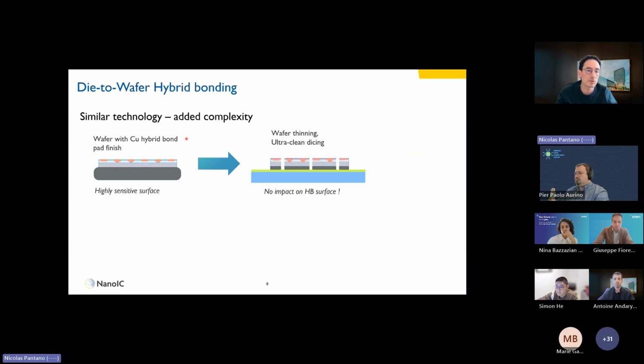I would like to dive a little bit into the details of what die-to-wafer hybrid bonding is, just for your education. So you start with a wafer where you create hybrid bonding pads. Something very essential to understand is that hybrid bonding is a very complex technology. The reason is you need a wafer that is very flat. Just to give you a common sense, you need less than 1 nanometer variation in thickness over 1 micron of distance. So there's a factor of thousands here between both axes.